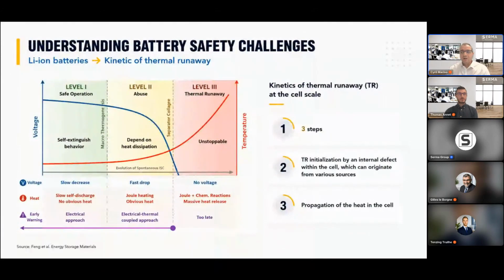From theory now, at least from a kinetic point of view, with thermal runaway you will hear a lot of stories about fire brigades that try to put a pack into water, and after 2 weeks they take it out and it starts again. The thermal runaway starts again. Here everything is kinetic. When you start to have an issue, an internal short circuit in your cell for example, there are different moments where you can stop, or at least limit, the thermal runaway. You put enough cold in the system to limit the heat from dissipating and propagating.